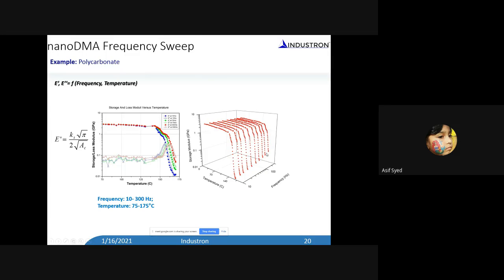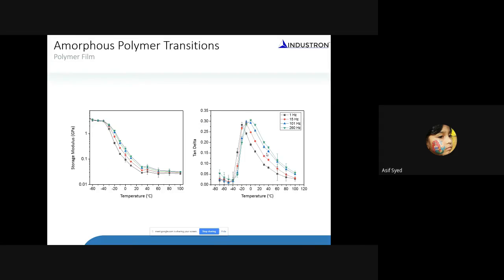That we call superimposition. Basically, we can measure at what temperature and what frequency the material properties are almost the same. We can figure that out. Okay, so this is very useful for polymer materials, and you can also go and measure the tan delta. This is for a polymer thin film.